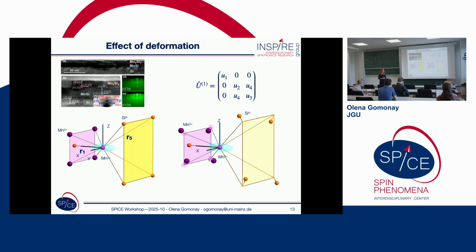So what I did here is straightforward. I fix these atoms, then I introduce all the vectors which connect a magnetic atom with a non-magnetic environment. And I construct a kind of tensorial value and sum over all these atoms. And then this gives me a symmetry. For example, if it would be a cubic symmetry, then I will have some non-zero contribution only along Z, X, and Y, and the rest will, by symmetry, be cancelled.